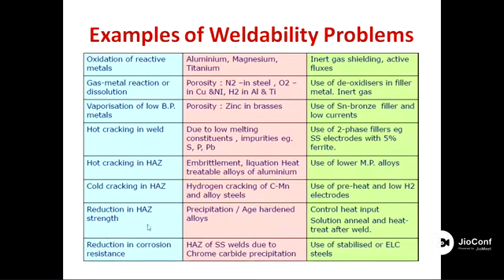The reduction in heat affected zone strength. So I mentioned to you that in welding of some precipitation hardenable aluminum grades, the hardness or the strength drops because of this welding process. This kind of behavior is because of the high heat input. So we have to control the heat input, and we have to control the parameters of solution and heat treatment after welding.